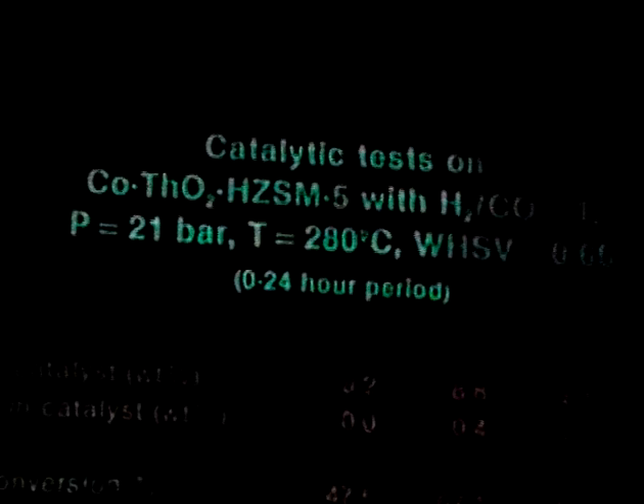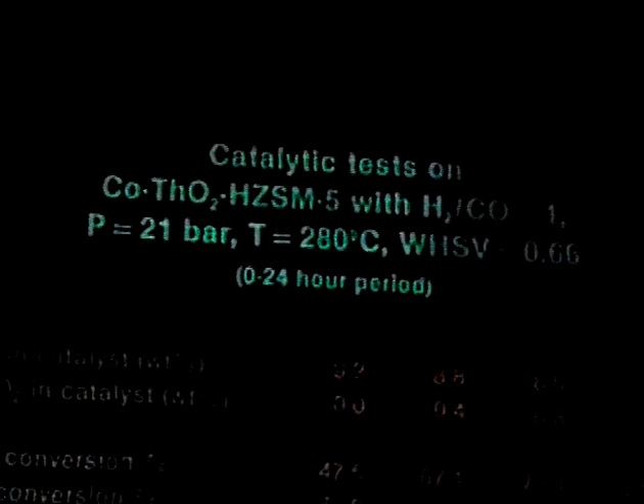The studies we did were based on cobalt ZSM 5 catalysts promoted with Thoria. Here you see a number of catalysts containing cobalt and ZSM 5. The percent of cobalt in these catalysts is about 9 weight percent, and we added various amounts of Thoria ranging from 0 to 1.5 weight percent as a promoter. The experiments were done with a hydrogen to CO ratio of 1, at a pressure of 21 atmospheres, 280 degrees C.